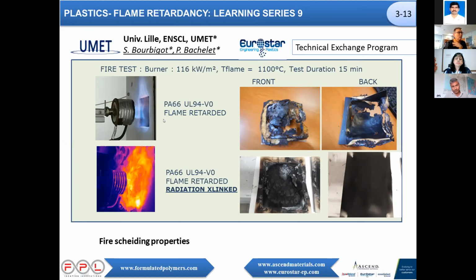So even a polyamide, which is flame retardant, resistant to fire, after the testing really vanishes. There is nothing left. If you take the same material cross-linked, then you see on the back plate, you keep some kind of char and integrity. So we have a lot of customers now in many fields that are thinking of using cross-linkable plastic for shielding against fire. We are no more talking about high resistance, but extreme resistance.